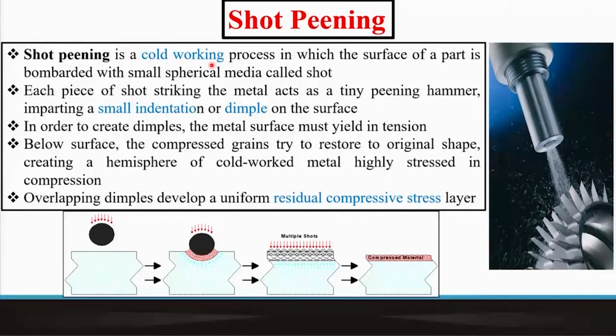So it's basically a cold working process. You're not changing composition. You're not subjecting to any high temperature or any thermal activation. Purely by cold working, that means you're deforming a very controlled layer from the surface up to a limited thickness, introducing a certain amount of dislocation density, and creating plastic strain with a purpose to actually confine the deformation within a small region, so that eventually the material that gets deformed would like to regain, and in the process should develop a residual compressive stress.